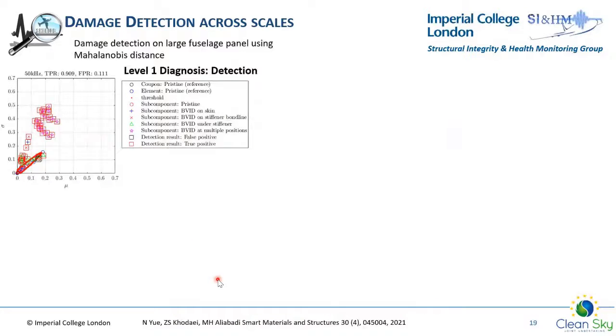So putting everything together, level one really is focusing on detection. So the result that you see here based on the Mahalanobis distance is detecting damage that exists in coupon, element and subcomponent. So combining the threshold for all of that, which has been developed at a material level, we can have a very good detectability, because the false positive rate here, you can see that it's 0.1.